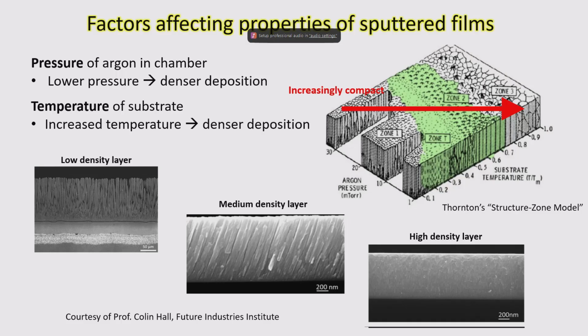So it tends to be that the lower the pressure of argon that you have in the chamber, the better, the more dense the deposition is. You can perhaps think of that as there are fewer other argon atoms to interfere with each other, and therefore you have a better transfer of material from target to substrate. The other important factor is, and this is almost always done, to moderate the temperature of the substrate. So between those two factors, there's this model which says if you want a denser coating, then run at a lower argon pressure and also increase the temperature of the substrate. These are dramatic examples and I got these from Professor Colin Hall here at the Future Industries Institute. That shows the difference in structure.